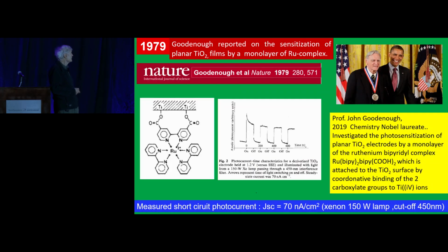And so we were not the first. In 1979, I met with John Goodenough. At that time, he was a professor at Oxford University. And he had come up with a sensitized TiO2 system where a ruthenium complex was the light absorber. And he had correctly thought to attach it through these carboxylate groups at the surface so that the absorption would be self-limiting. So you dip the film in a solution and a monolayer is formed, then it stops because all the sites that can attach the molecules are filled.